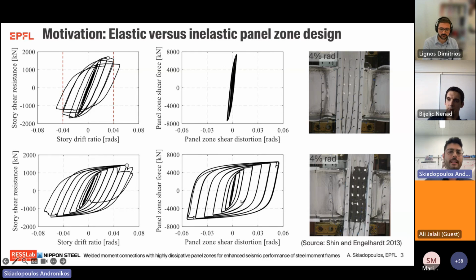However, if we assume a nominally identical beam-to-column connection in terms of dimensions and cross sections, while in this case we intentionally weaken the panel zone shear resistance by removing the doubler plates that are adjacent to the column, what we see here is that the connection achieves a very stable hysteretic response at 4 and even at 6% story drift ratio. And this is because in this case we enable the inelastic deformations of the panel zone, and therefore we take advantage of the beneficial aspects of panel zone shear yielding. This connection reduces the potential of structural repairs due to the delay of beam local buckling, as you can see characteristically in the bottom right, far right figure.